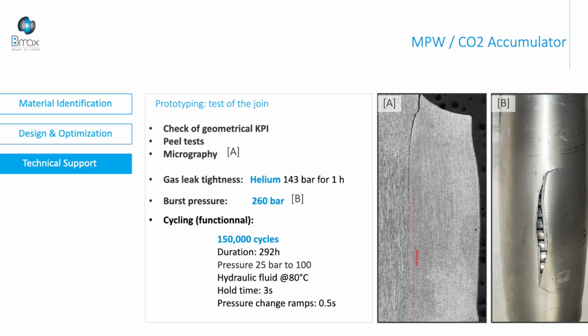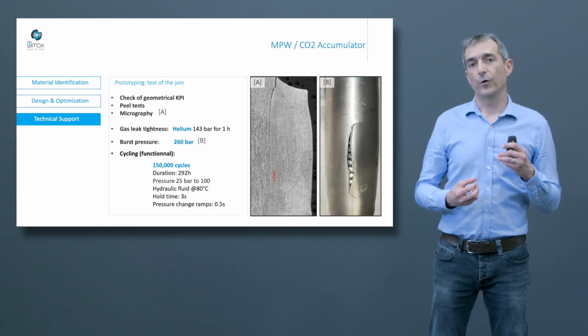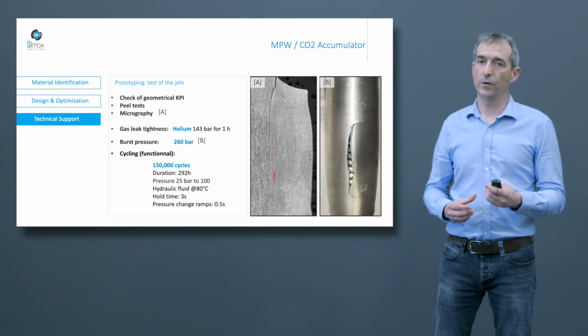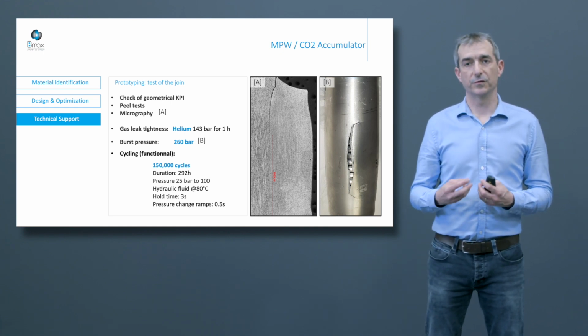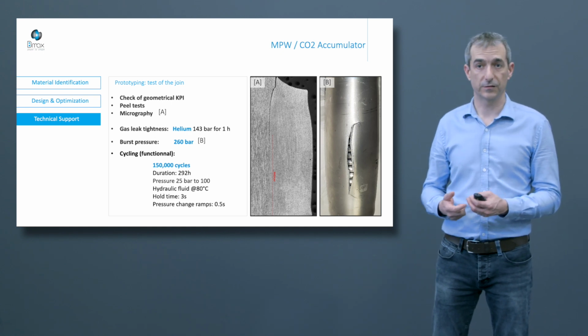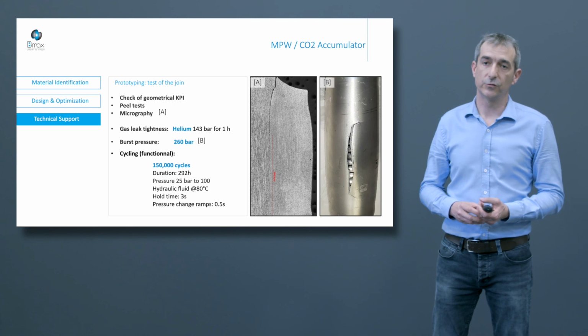The next step is to build the prototype and to realize the first test. And with the first assemblies, we can check the geometry, the geometrical KPI, key point of interest. We can perform peel tests and analyze by micrography the length of the welded area. After, the customer checks the helium leakage, 143 bars during 1 hour. It performs a burst pressure test, 260 bars. And for the functional requirement about the cycling, it performs 150,000 cycles during 292 hours.